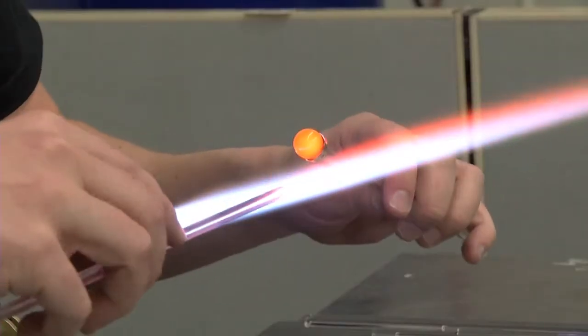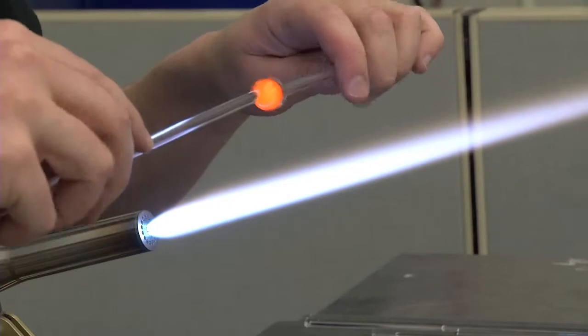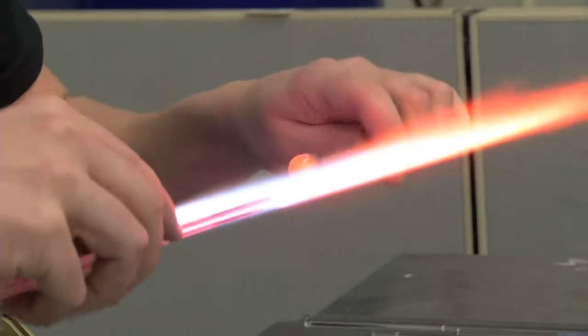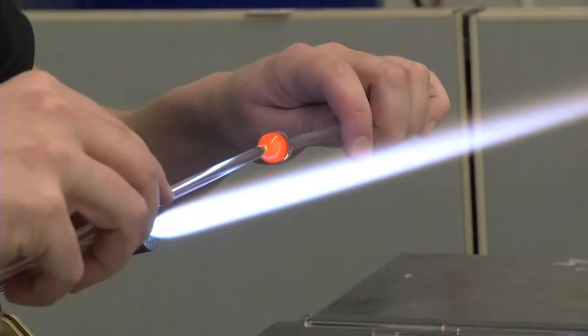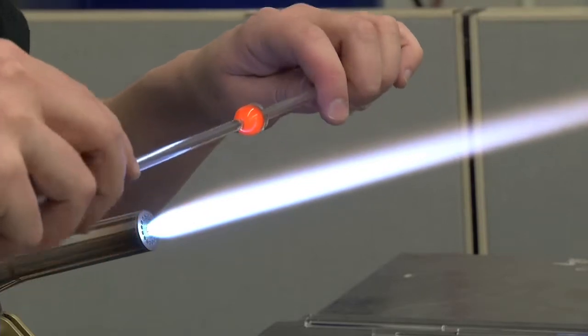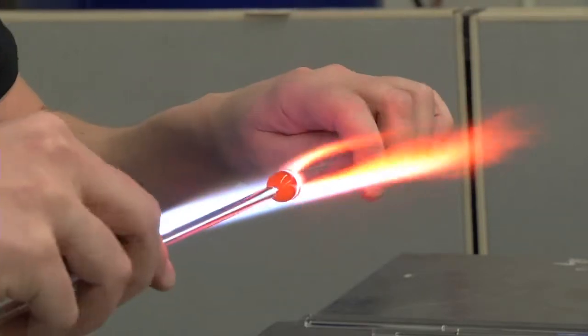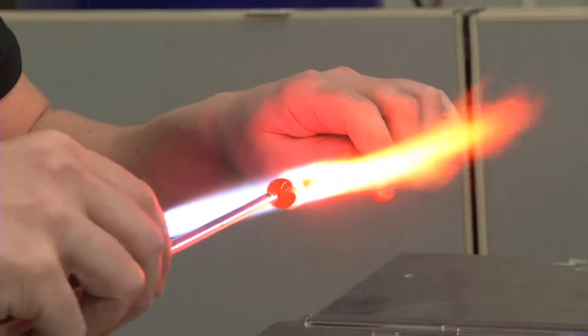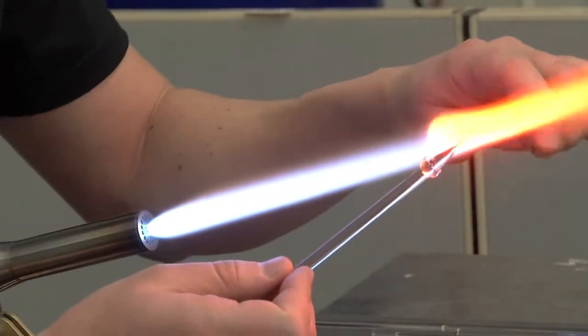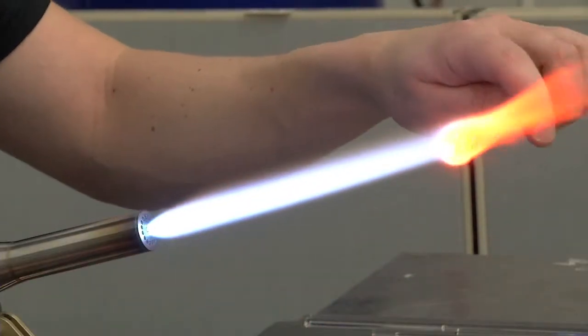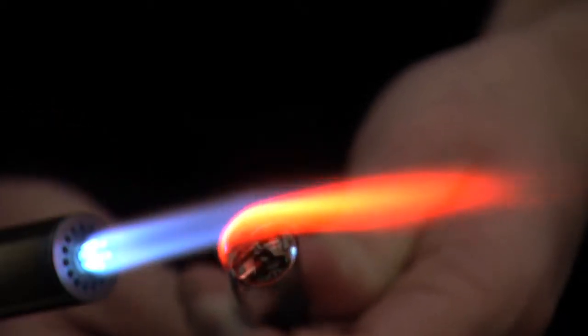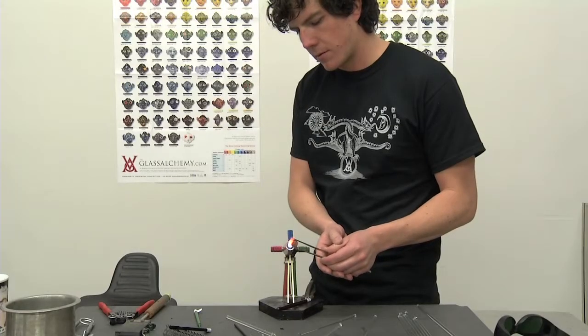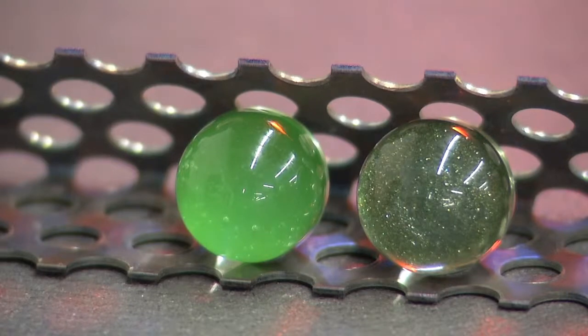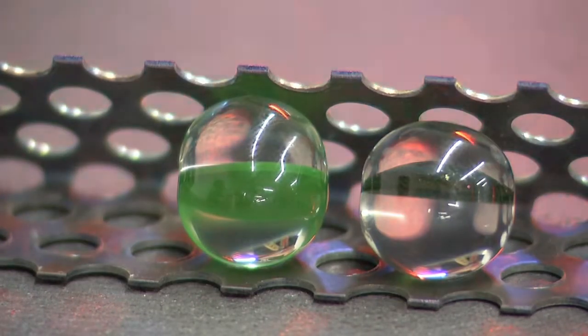Prior to burning off the extra punty rod, cool and tug while the glass has a slight orange glow. At this point, the glass is too stiff to move, but the process of putting the glass under tension aligns the sparkles. Burn off the extra punty rod and round the gather into a marble shape and place in the kiln at 1050 for 1 hour. You are successful if there is no checking or cracking.